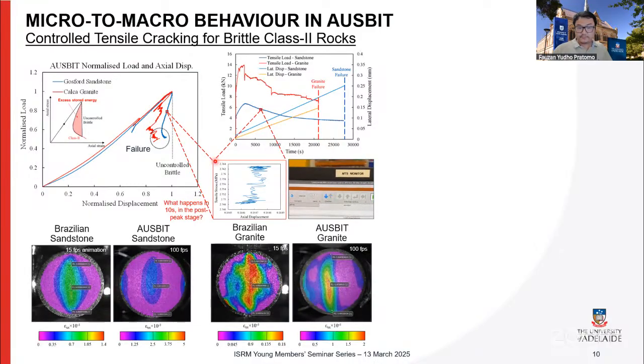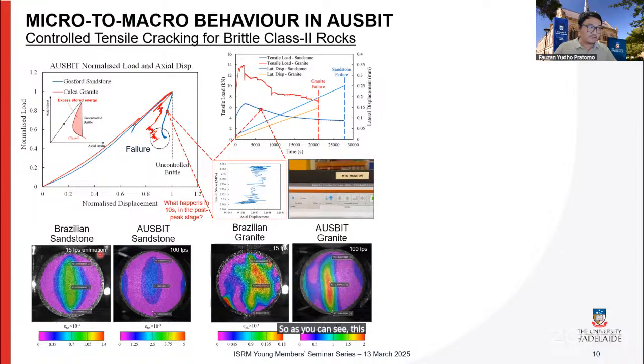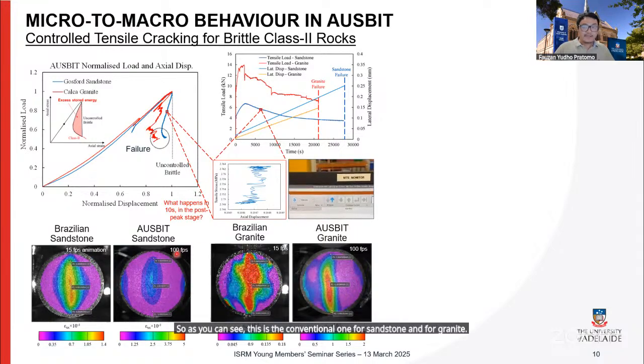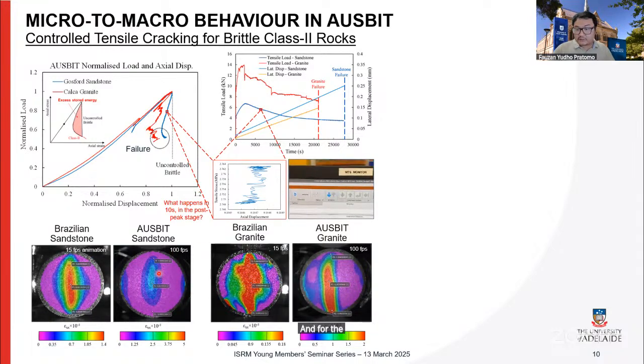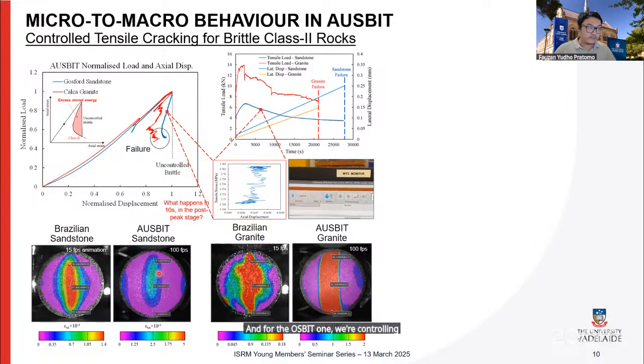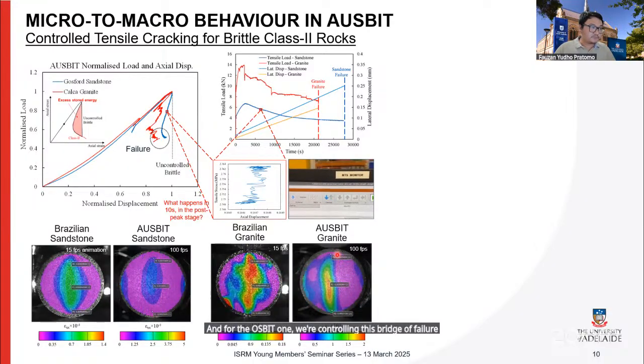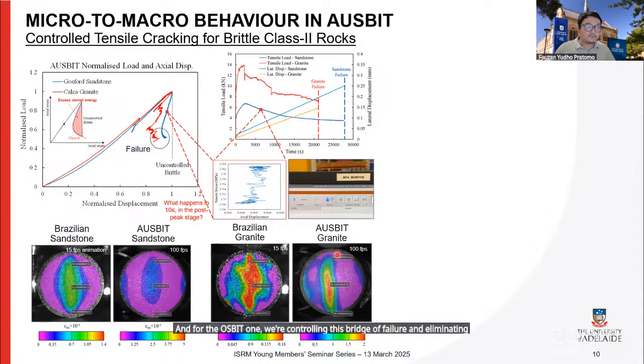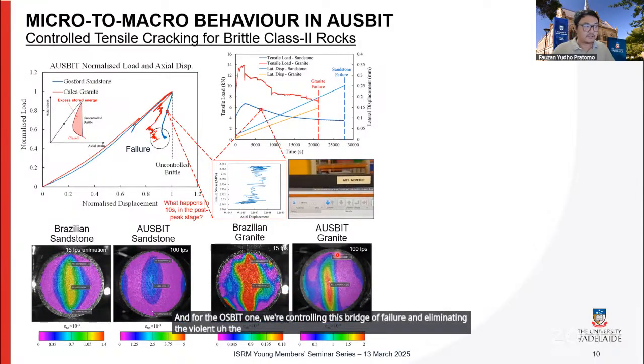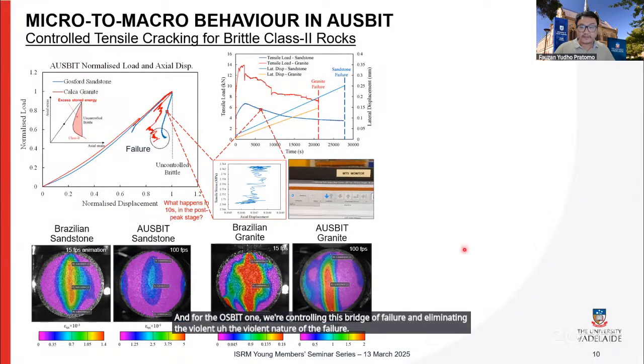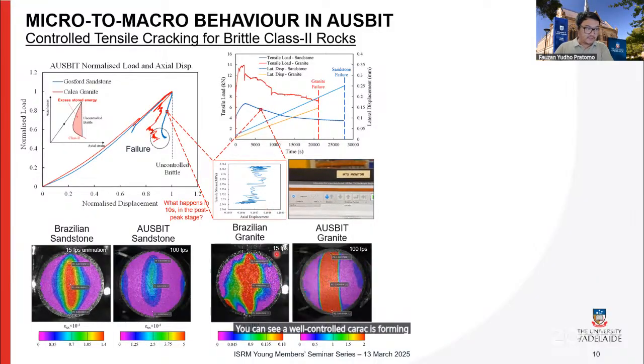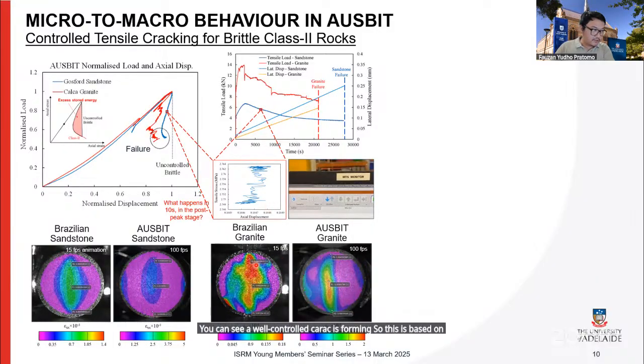So as you can see, this is the conventional one for sandstone and for granite. And for the AUSBIT one, we're controlling this brittle failure and eliminating the violent nature of the failure. You can see a well-controlled crack is forming. This is based on the DIC recording.